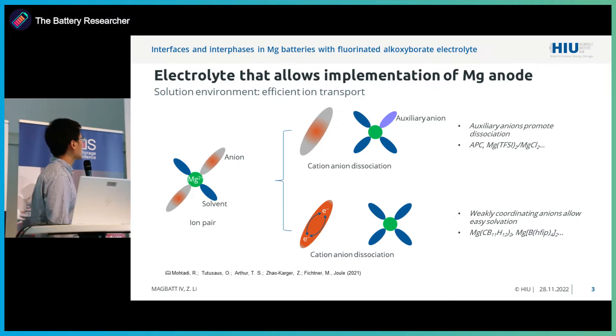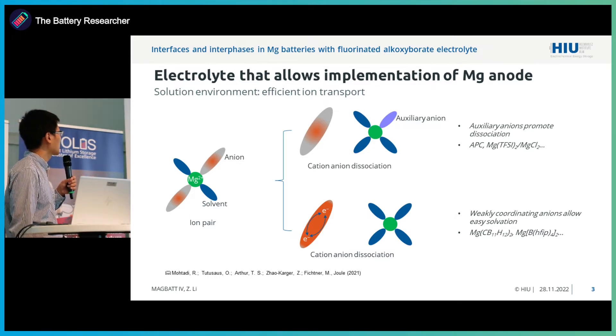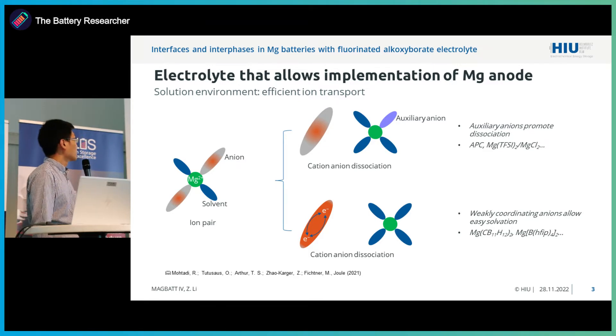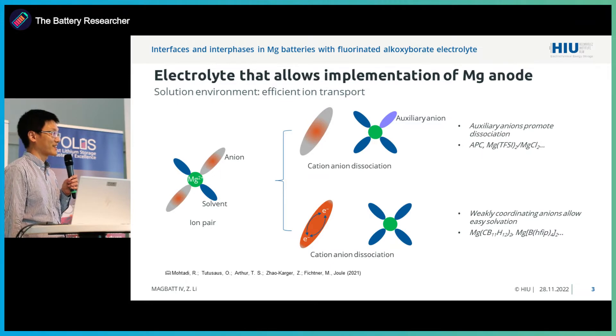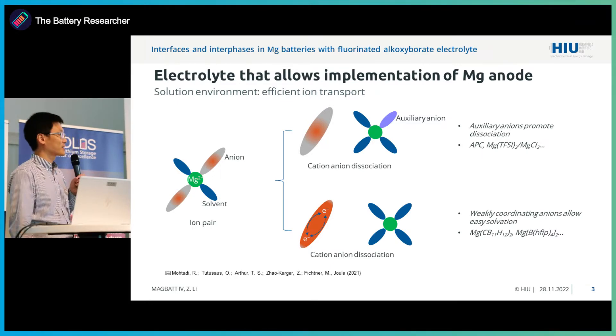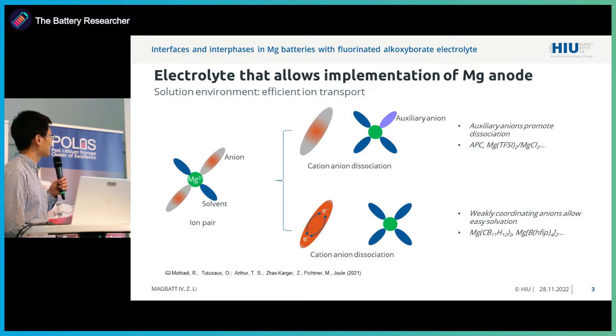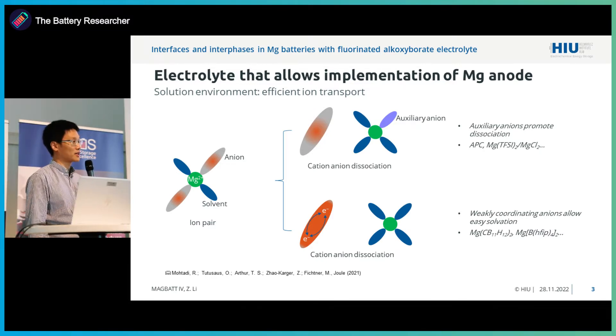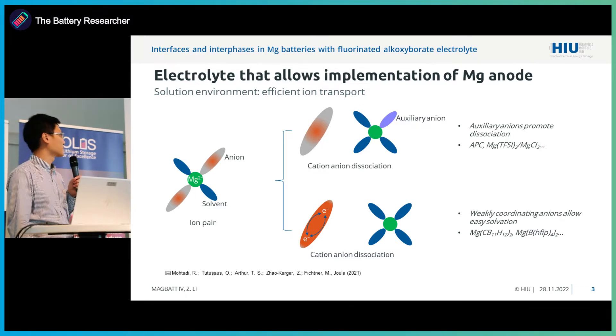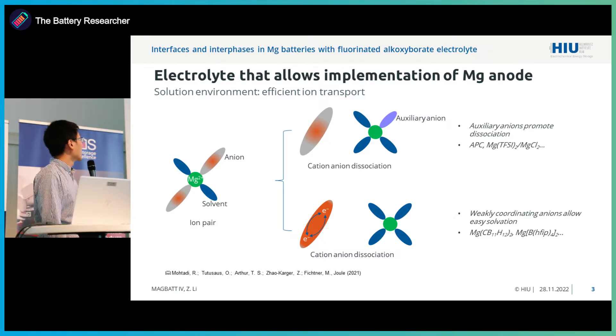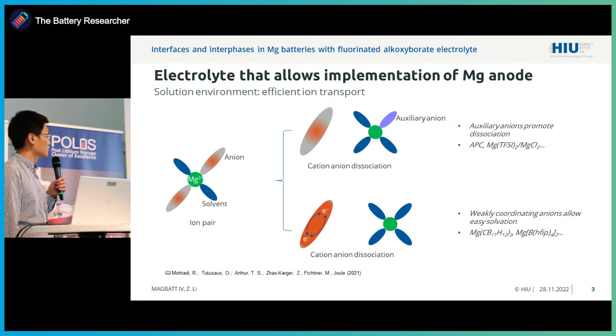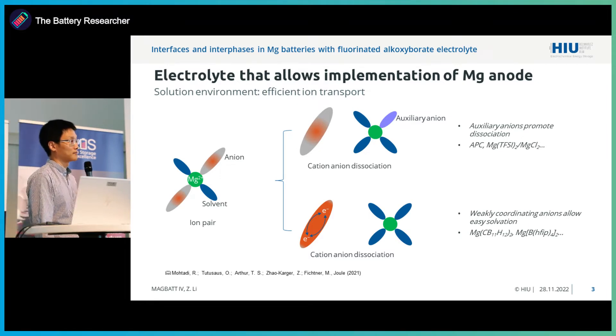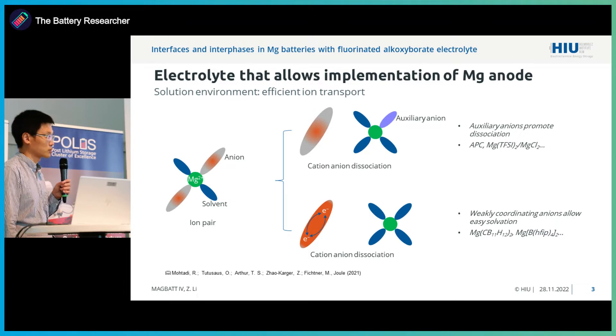The plating and stripping process of magnesium is mainly governed by the electrolyte, which is in direct contact with the magnesium anode. If we look at the development of magnesium electrolytes, it is not straightforward. We have a lot of struggles, because we are dealing with divalent magnesium ions which interact strongly with counter-anions. In many magnesium compounds, we see ion pairing, which is much more significant than in a monovalent system, leading to very limited solubility in non-aqueous solutions and insufficient ion mobility.